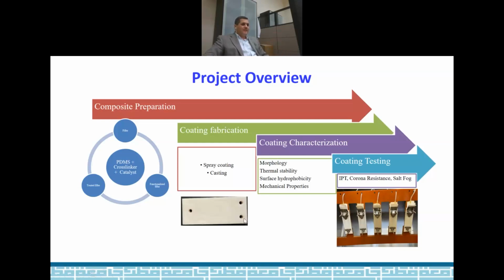You see, this is a typical sample that we make in labs at Qatar University and also at Texas A&M with Dr. Ahmed Abdullah's group. We spray coat the coatings, whether that coating has a filler or not, on a ceramic. This is a typical ceramic tile that is accepted by the electrical engineering community. We coat our coating on this kind of tile, and we make these three holes in order to later test the performance of the coating using what's called the IPT test.